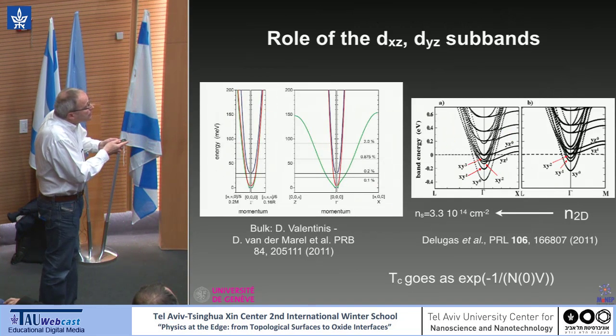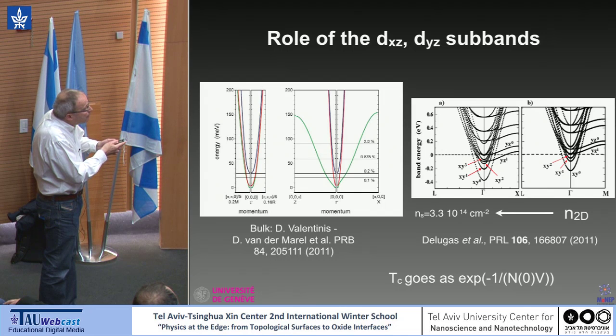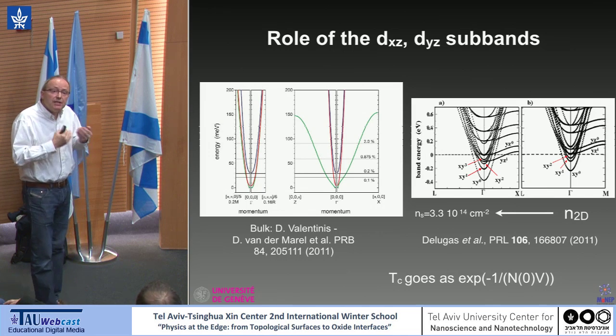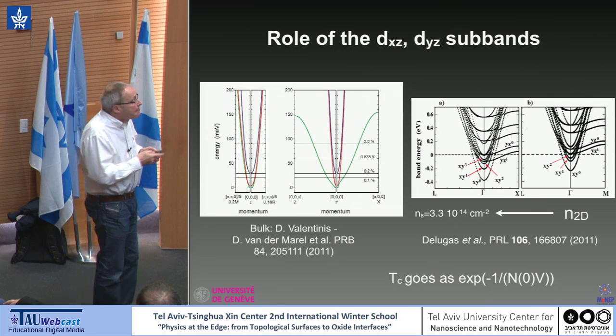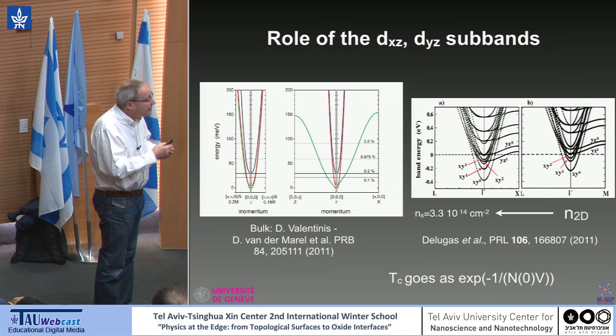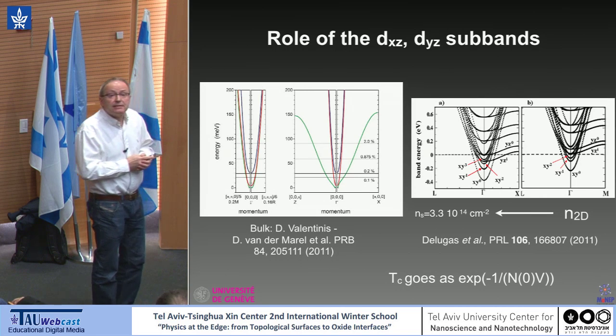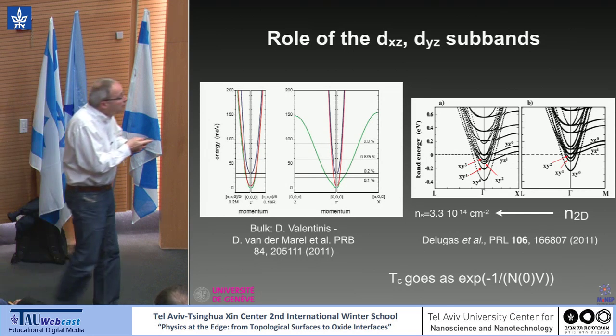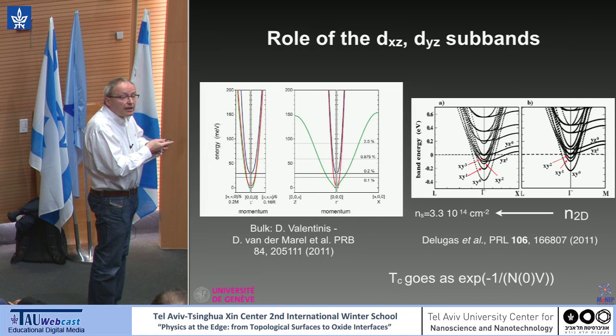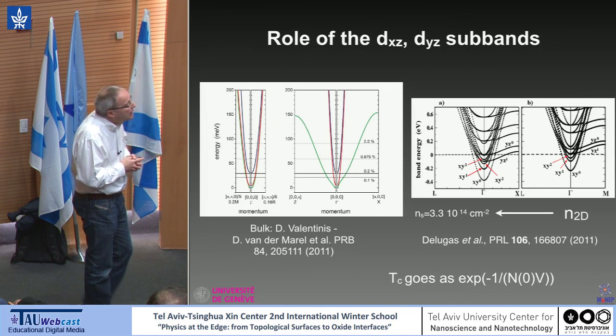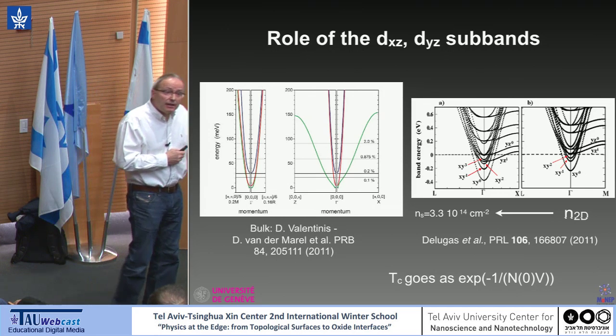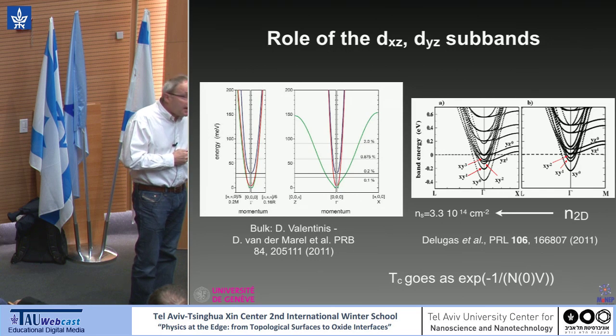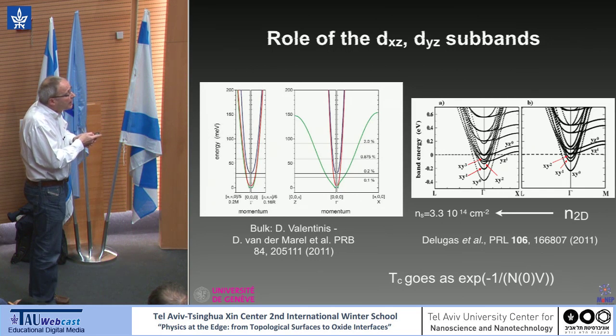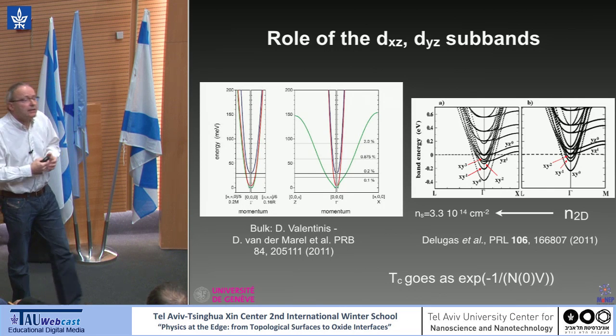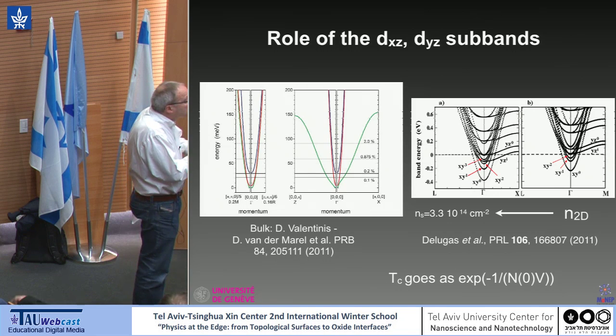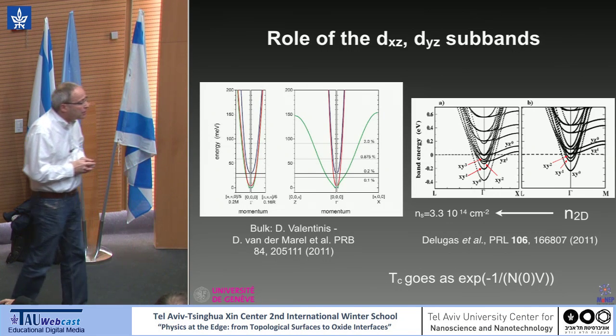In the bulk, you see the electronic structure in the bands, but very quickly, as you fill, the system is finding heavy electrons. At the interface, because of this electronic reconstruction and confinement, the first bands are very light. So the proposition is that these XY bands are leading to a very low TC. You know that TC goes as an exponential of the density of states, and a light band means a low density of states. This is backed up by recent calculation from Davide Valentinis, using, by the way, Kamran Behnia's data to extract the coupling parameters. It shows that as long as you're not touching this XZ, YZ band, TC is essentially 0.